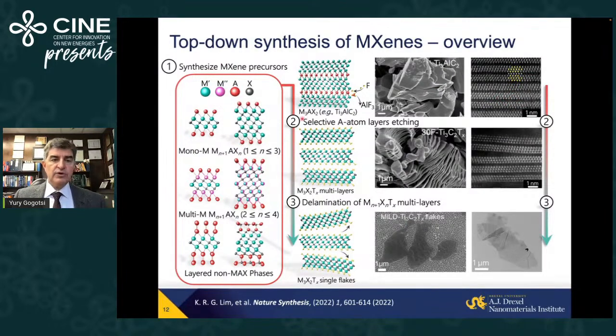The next thing, great to have theoretically many, many different materials, but can we make them? Can we make them in large quantities? And the idea here is that these materials are produced by wet chemical etching or molten salt etching, which I'm not going to talk about today, or other extractive synthesis, like we made carbide-derived carbons from carbides before, taking transition metal or silicon or boron atoms from carbides. We take layered carbides, which are known as MAX phases. They are not the only ones. And we remove from these carbides, by etching in either acid, molten salt, halogens, or electrochemical etching, a monatomic layer of an element,